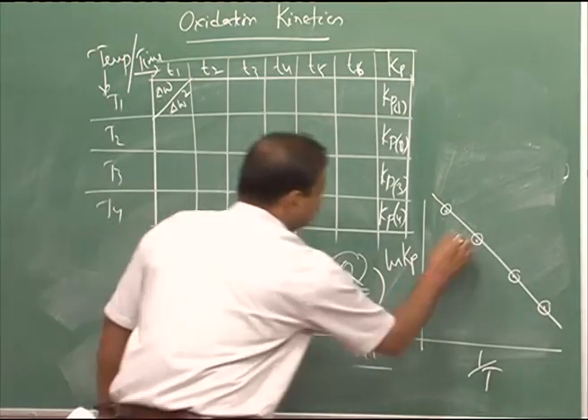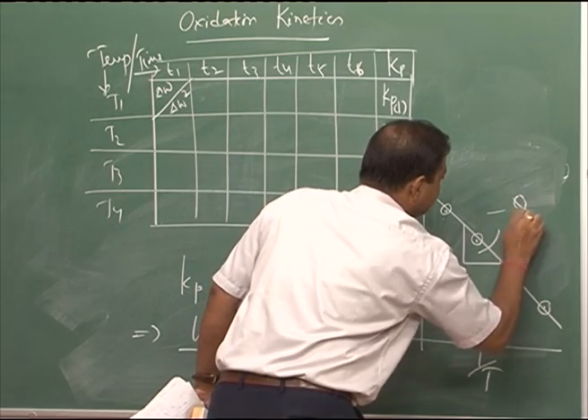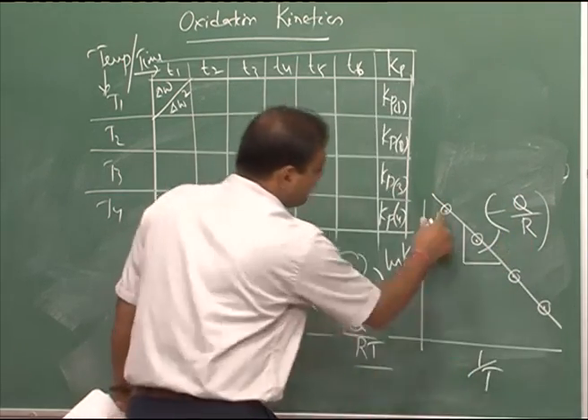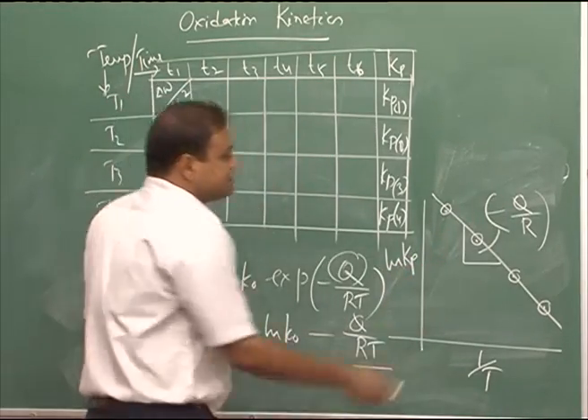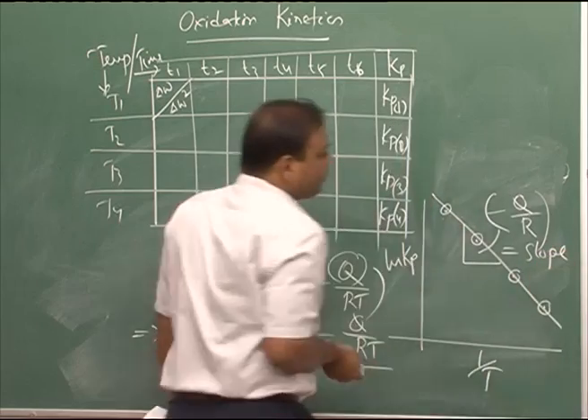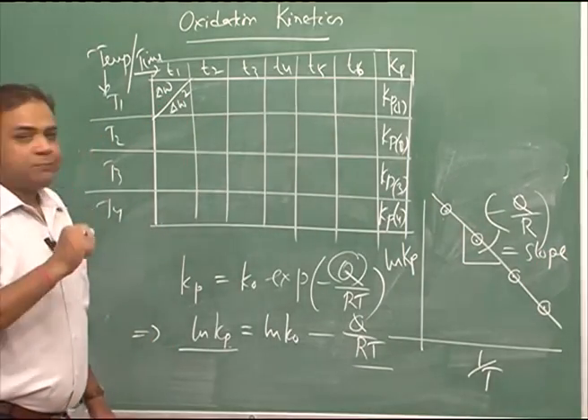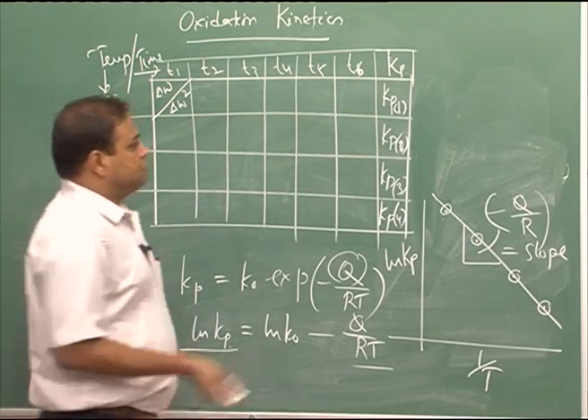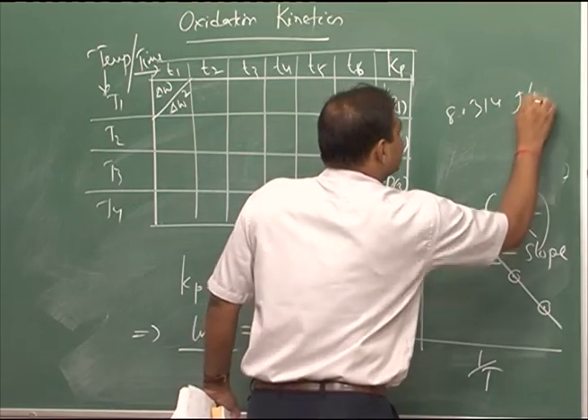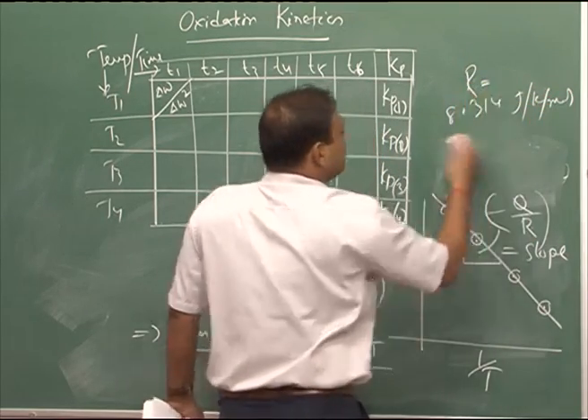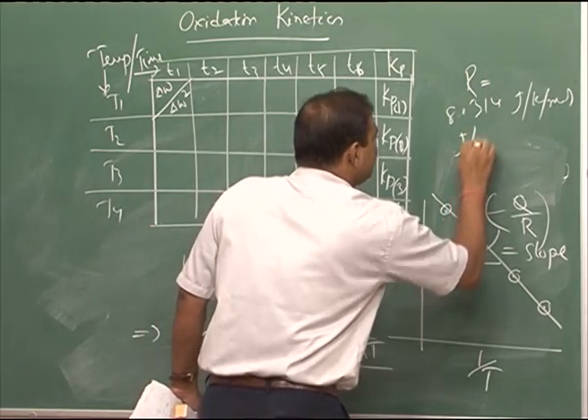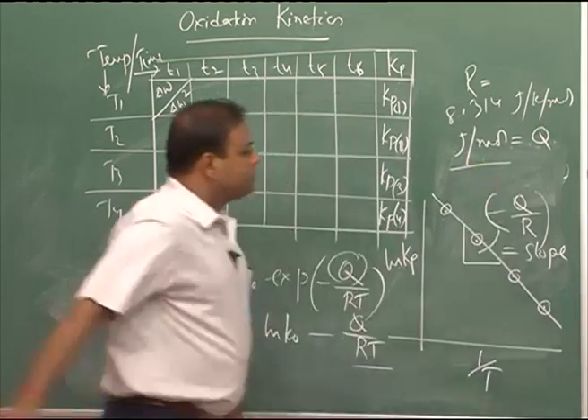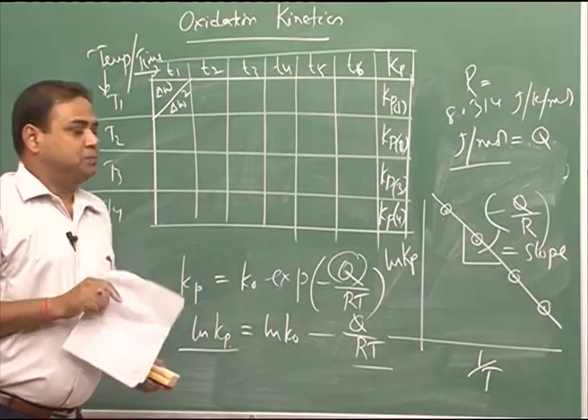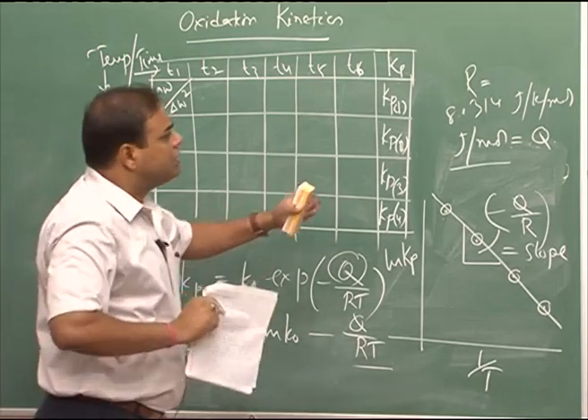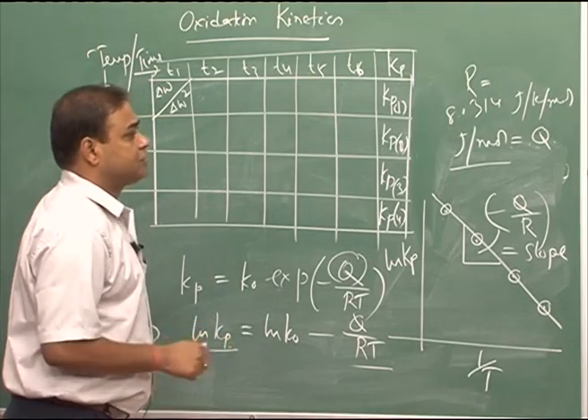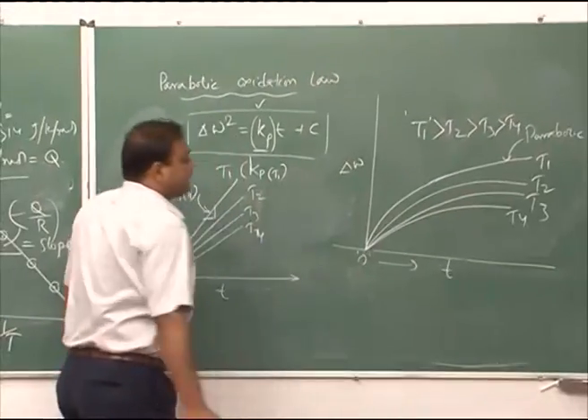After doing linear fitting, we see that the slope would give you the value of minus Q by R. So, we find out the slope and equate it to minus Q by R, and putting the value of R as 8.314 joule per Kelvin per mole, we can get the value of Q in the form of joule per mole. So, from this process we can find out the value of Q, and this entire technique is called the isothermal technique, because we are carrying out oxidation at a particular temperature.